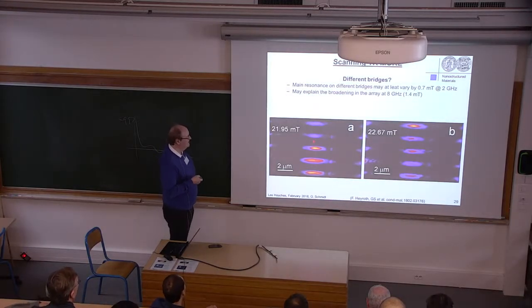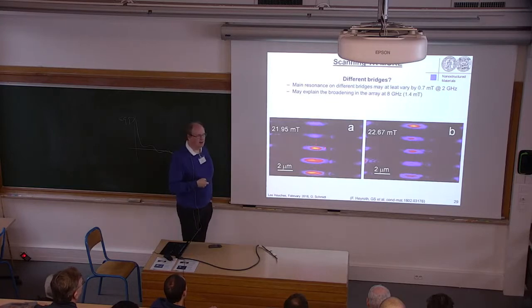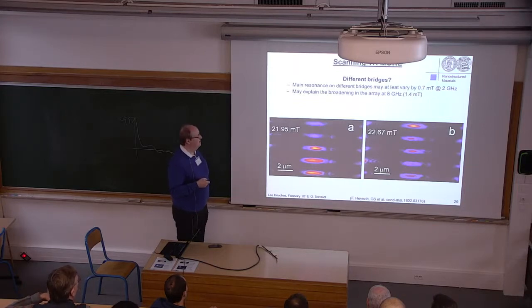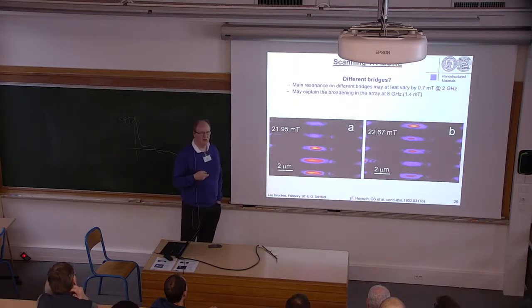If you look at different bridges, they come to resonance at different fields. But this is about 0.7 millitesla difference. But this fits the broadening of the line to 1.4 millitesla.